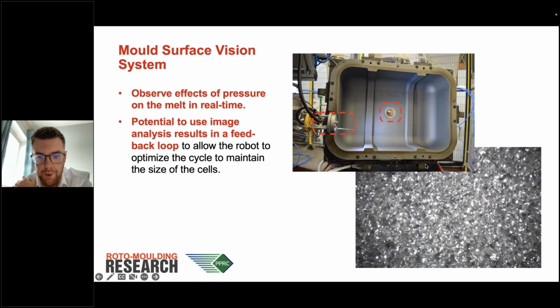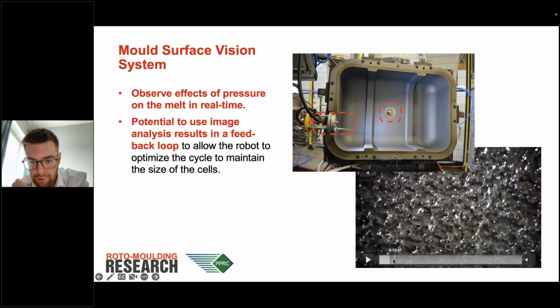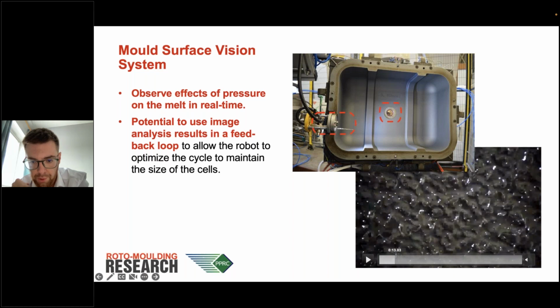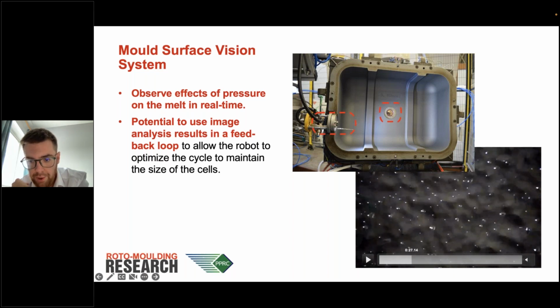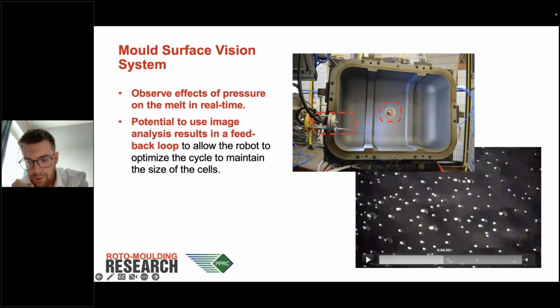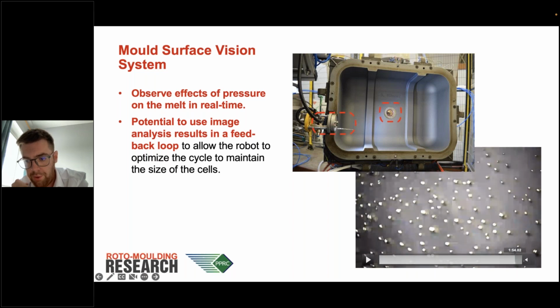So at the same time as doing that, I had developed a system for monitoring the vacuum foamed samples. So pulling a vacuum on a polymer melt that has bubbles already existing in it to create larger bubbles. So the same idea applies here, and you get this polymer melt that builds up on the wall. And then at this moment, you can pull a vacuum and you can see those bubbles start to increase in size. Now this happens fairly slowly because of the size of the mold and the size of the vacuum line that we were using on this machine. And then it moves into the solidification phase.